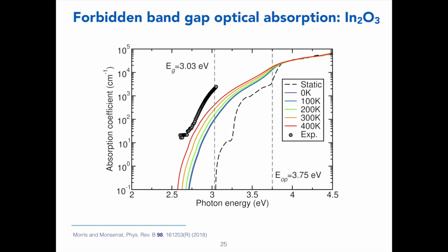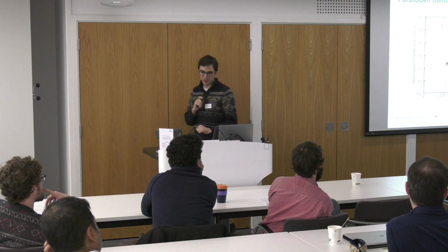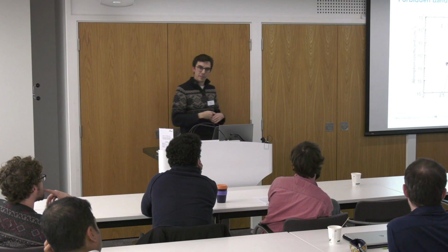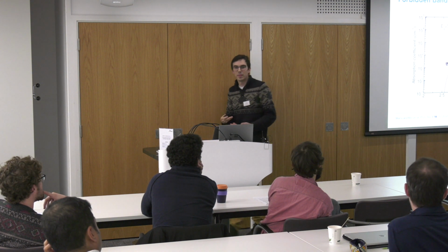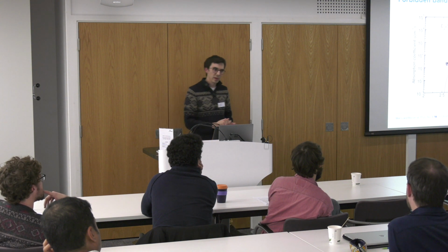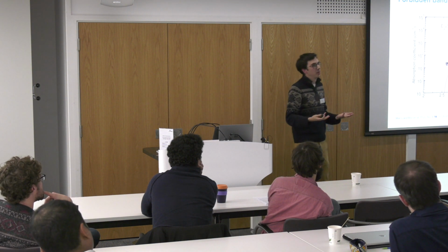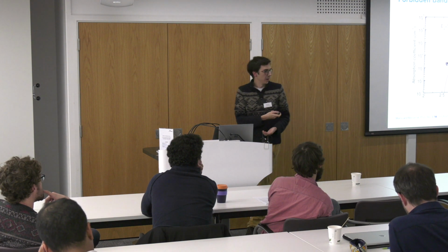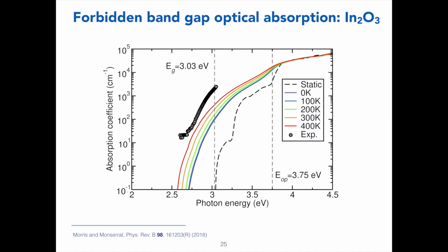Again, we can do this as a function of temperature, and again, even at zero temperature, we have a significant difference from the static lattice result, a purely quantum effect. And we're still somewhat underestimating the experimental results, and that probably comes from the fact that we only include dynamic disorder, but static disorder is also a mechanism by which you could enable these transitions to occur, again, because it breaks the inversion symmetry of the system. So probably by including static disorder, we would bridge the little gap left between theory and experiment.